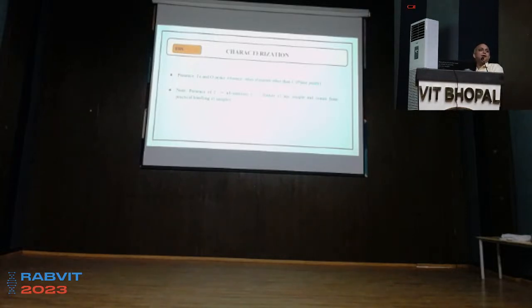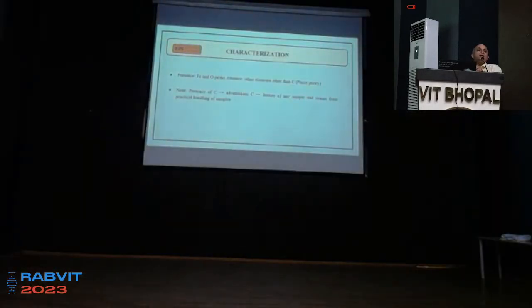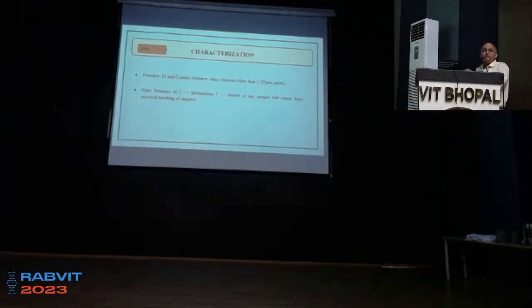Anyone? Okay. So EDX is an electron spectroscopy technique, where you use electrons to bombard a material and throw out characteristic X-rays from the cations and anions that are present in the material. Those characteristic X-rays are specific to those elements, which can help us detect those elements. So from this EDX study, we could find that only iron and oxygen are present in this material. And the only other impurity is the adventitious carbon.